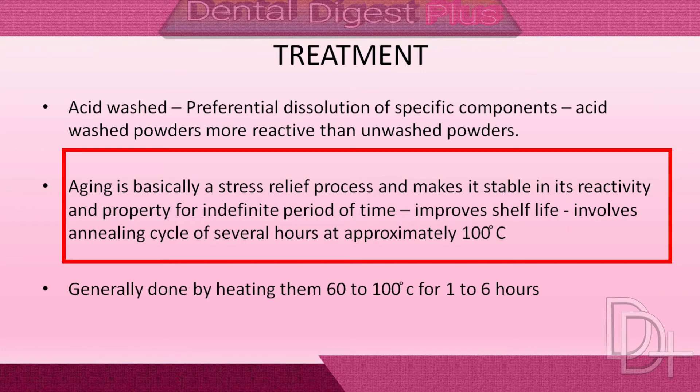Freshly cut alloy sets more promptly than aged particles, but some aging of alloy is desirable to improve the shelf life of the product. The aging is related to relief of stress in the particles during the cutting of the ingot.